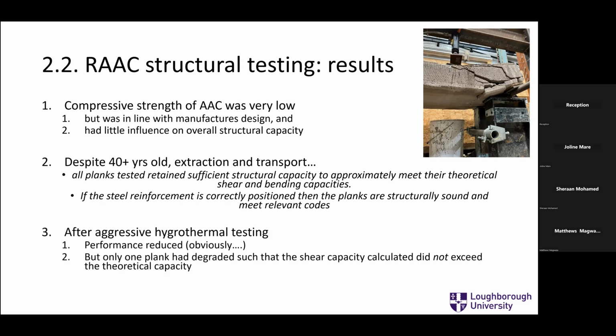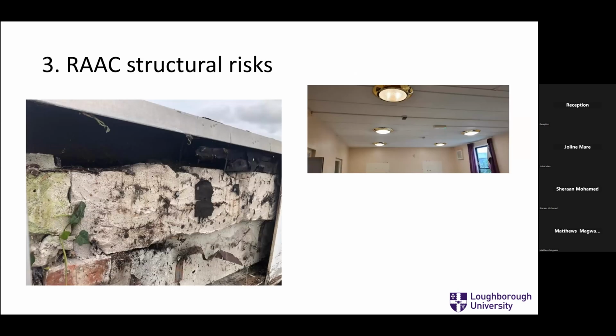Even after aggressive hydrothermal testing, so we put them in chambers, some of them, apply several days of intense rainfall, accelerated weathering, temperature cycles, plus 40, minus 40, and their performance reduced slightly, as any material would in that aggressive environment. But still, they, in general, bar one plank, took enough load, even after that very aggressive hydrothermal testing. So I think we're probably surprised at this. So then you might be thinking, well, what's wrong with them? What's all the fuss about?